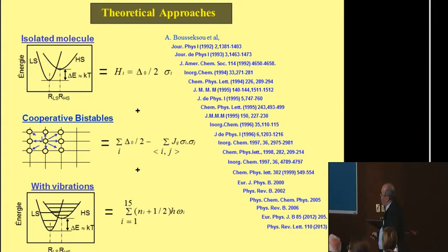And then when you go to the crystal, you can add interactions between molecules by your J, like an Ising-like formalism, okay? And then if you look at the vibrations in both states, because we have a change of the volume, you have to add the vibrations through a harmonic oscillator here, because the vibrations are different, the volumes are different. So that means that spin crossover materials are the addition of these three terms: isolated molecule, interactions, and vibrations.